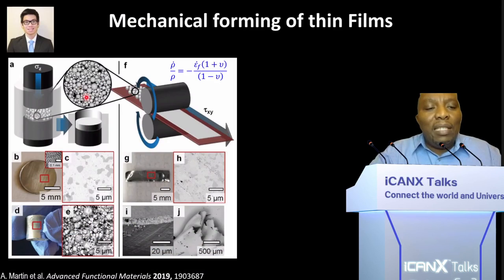But the challenge with this approach is that, as we know in granular matter, if you apply force, the force tends to be spread to the walls of the container because it's flowing by point contact. So the densification is not very good at the core, as you can see in this image here. However, if you look at how strain propagates in these kinds of materials, you realize that it's very dependent on the Poisson ratio, and so if you apply shear stress, you're more likely to get more uniform densification. And that's what we find here. We can make really nice films, even very, very thin films out of these particles.